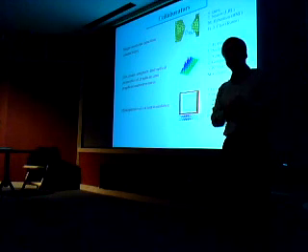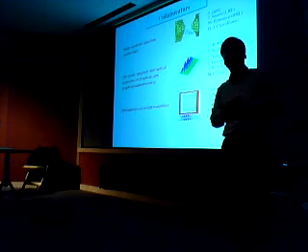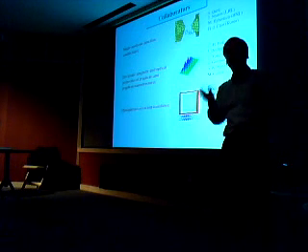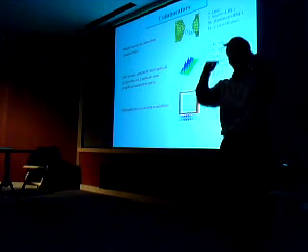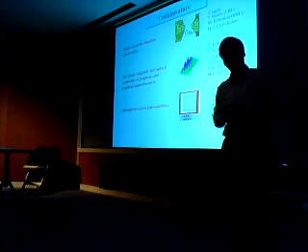But I think to a good degree that would give you the major correction, the first order correction to the problem we're looking at. Because we are two orders of magnitude or three orders of magnitude off compared to experiment. So the self-consistency and all that should be taken care of eventually, because as you say, if the levels are moved further or closer to the Fermi level, charge transfer will be different and so on. We haven't really taken that into account.